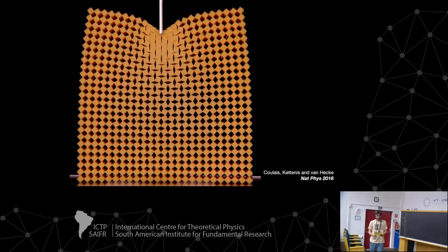Okay. So what do you think happens? Why are these rotations not uniform? I told you the mechanism by finite rotating energy. If you need to compress the entire structure, then you have a lot of this energy, so you can also compress some of the elements locally. The argument of Ben is that if you have 25 by 25 squares here, you have a few hundred torsional hinges. And so the bigger your system gets, the more energy it costs. And so the system finds a way to do things that are energetically cheaper.